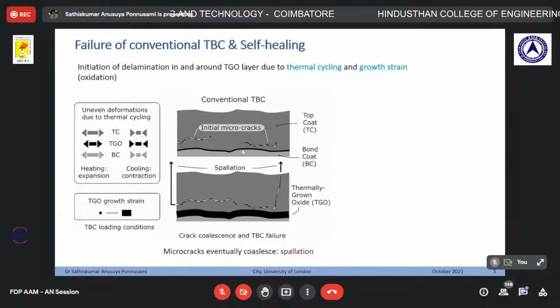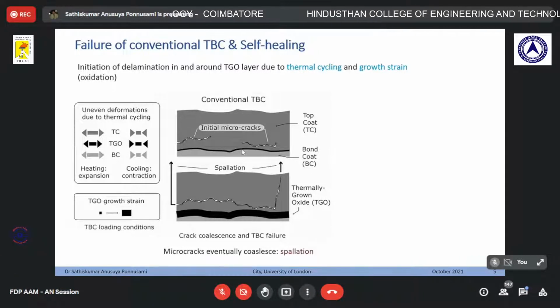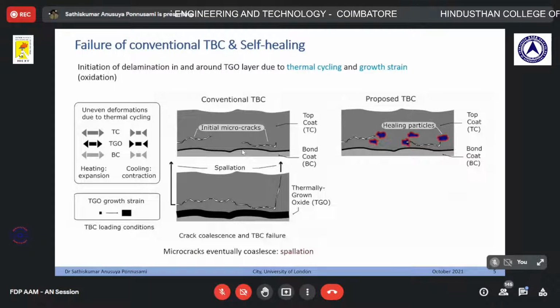Okay, and what is the other way to go? Of course, you can try to improve the coating by manufacturing techniques, introducing new different materials for coatings and so on. But then you are not able to prevent the damage, isn't it? Because you need to fly, which means you will create stresses, which means you will get cracks. Okay, so that is unavoidable. So what we actually proposed in this particular project, which is of about 5 years of research worth 5 million euros during that time between 2012 to 2017, what we did is we proposed the following that you see on the right. And you see the little particles over there with a red color boundary. Yeah, and those are called healing particles.